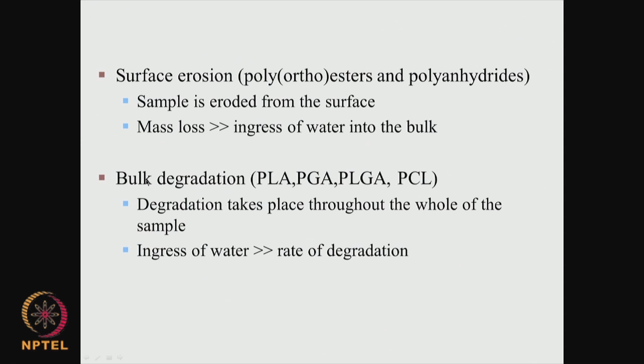Okay. I also mentioned surface erosion, that means the material gets eroded slowly on the surface, or bulk degradation. In bulk degradation maybe water ingresses very fast and then the degradation happens. It could be acid catalyzed hydrolysis or autocatalytic type, whereas in surface erosion the mass loss is much faster than the ingress of water into the bulk. Both types of systems have their advantages and disadvantages. In surface erosion, the material will become thinner and thinner. In bulk degradation, the material can one day completely disappear. For surface erosion, polyorthoesters and polyanhydrides. For bulk degradation, you have polylactic acid, polyglycolic acid, PLGA, PCL and so on.